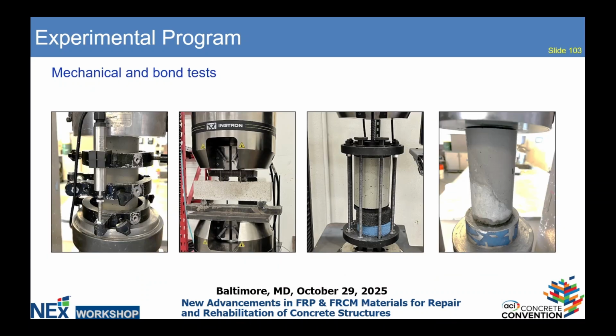So for the test side, we did 4 different types of tests. One is the regular compressive strength and modulus of elasticity test, then the flexural test, and we also did 2 more tests on the component level, that is the bond test. On the third figure, you can see a pull-out test being performed on a block of polymer concrete. It is a number 4 rebar, grade 60, with 8 times the diameter, which is 4 inches, embedded inside the concrete. We found that 8 d_b was sufficient in the case of a regular specimen in a prior research, which we used here.